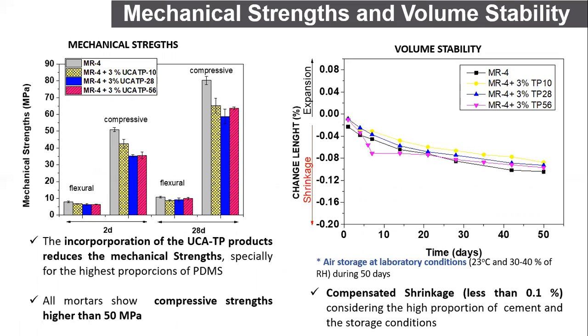With respect to the volume stability, all mortars show a compensated shrinkage lower than 0.1% after 28 days, which is not too bad considering the high proportion of cement in the repair micromortar, as well as the severe drying conditions. And these mortars were stored at laboratory conditions at 30% of relative humidity and 23 Celsius degrees.